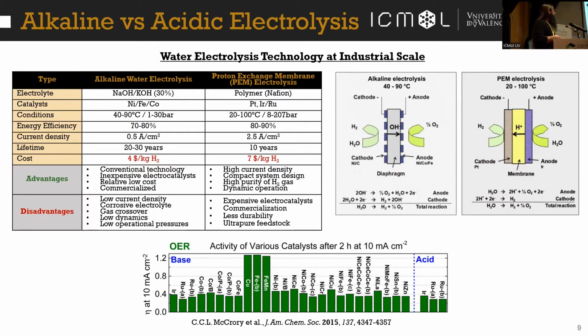So regarding the catalysts that are used in these systems, in the alkaline electrolyzer, mainly first-row transition metal oxides are used because they are very stable under basic conditions. And as you can see, some of them work really well, so they are very easy to implement. On the contrary, with the PEM electrolyzers, only iridium and ruthenium-based materials can be employed because they show relatively long stability under these strong acidic conditions.